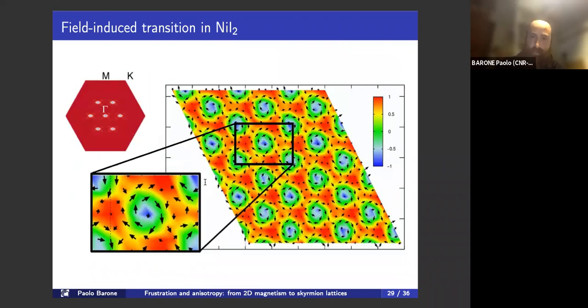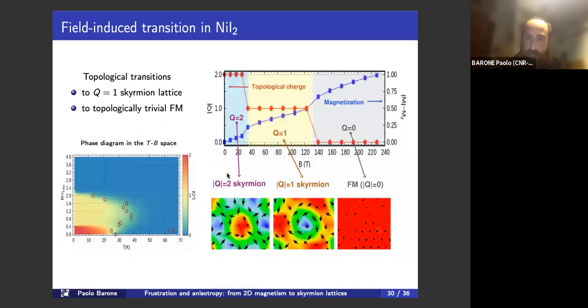Even more interesting, if you now apply a magnetic field, at some point we see a field-induced transition. Here again, I plot the spin structure factor, but you see that there is an additional peak at the gamma point. That simply means that there is a net ferromagnetic moment in the system, which is induced by the applied magnetic field. And now the lattice is formed by a different topological object, which is nothing else than a Skyrmion, a Q=1 Skyrmion. So we also have a sequence of field-induced topological transitions in the system, where we can use the field to go from an anti-Skyrmion to a Skyrmion, then eventually to a trivial ferromagnetic phase.